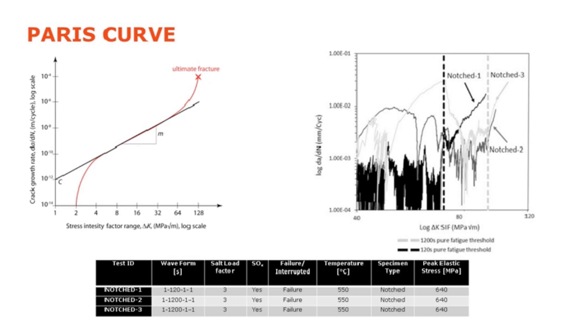And what's quite interesting is to compare notch 1 to the notch 2 and notch 3 specimens. Notch 2 and notch 3 have a longer dwell, so there's more corrosion going on, but we actually see the crack depth at which they start to behave more like fatigue, or start to correspond to fatigue crack growth, is higher. So that's telling us that corrosion in this case is actually suppressing fatigue.